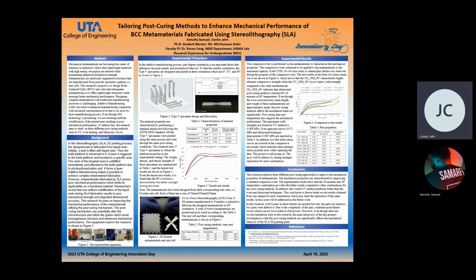Additive manufacturing makes it possible to achieve complex metamaterial fabrication. However, metamaterials fabricated by the SLA method show poor mechanical performance, and this limits their ability to be a functional material. Researchers reveal that non-uniform solidification of the liquid resin during SLA fabrication results in poor mechanical strength and degraded dimensional accuracy. This research focuses on improving the mechanical performance of the metamaterial using the post-curing process.